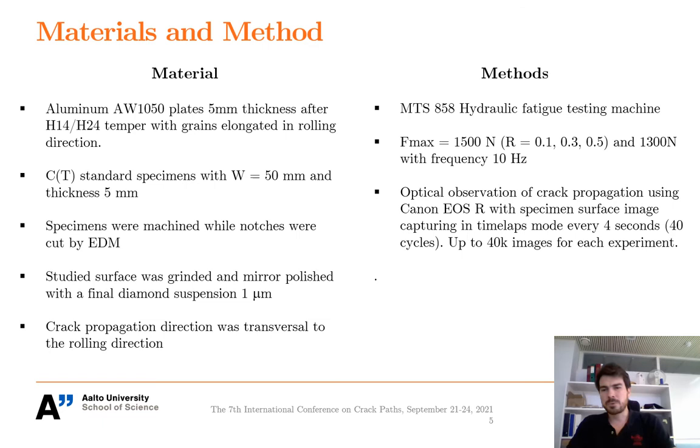To perform fatigue crack tests, we used MTS 858 hydraulic fatigue testing machine. We used two F_max values, 1500 and 1300 newtons. Where during 1500 newtons, we varied asymmetry coefficient 0.1, 0.3 and 0.5. And all tests were performed at the frequency of 10 Hertz. To provide crack length tracking, we developed an experimental procedure with optical observation of crack propagation using Canon EOS R, where the specimen surface was captured every 4 seconds in a time-lapse mode. So the difference between images were 40 cycles. And we used to collect about 30-40 thousand images for each experiment, and that was helping us to provide crack tracking during experiments with the following algorithm.